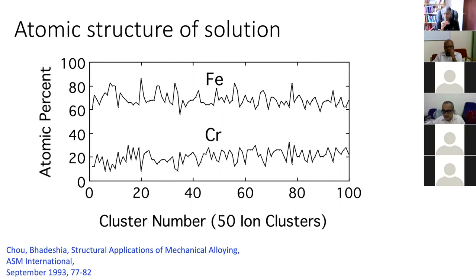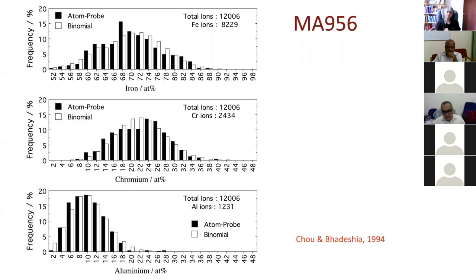So that is the real question to ask: if I have a completely random solution and I collect 50 iron clusters, then will I get something like this? The only way to answer that is to compare the distribution of compositions that we detect here with a binomial distribution. Here, for example, the black refers to the atom probe analysis and the white to the binomial. You can see that we basically get agreement with a random distribution of atoms, because this material is produced by mechanical alloying. So the atoms are forced into solution, as somebody mentioned in the last lecture.